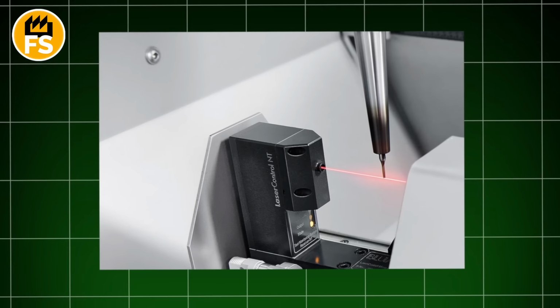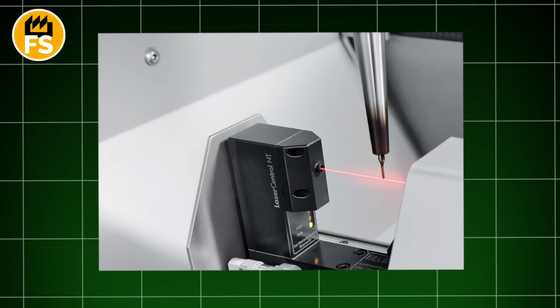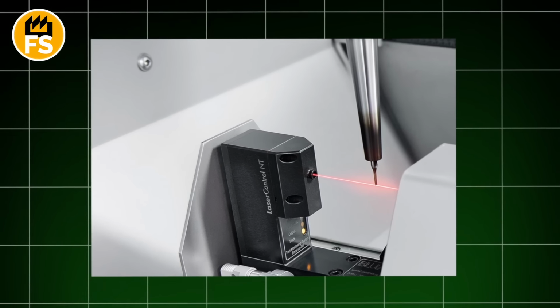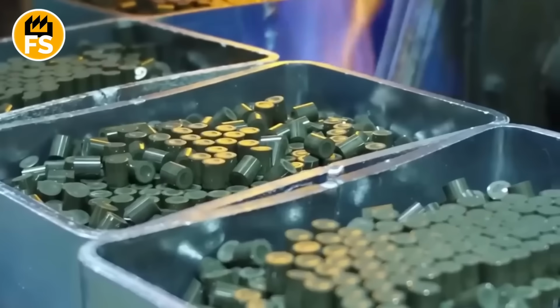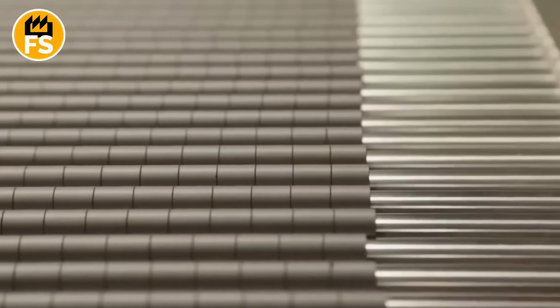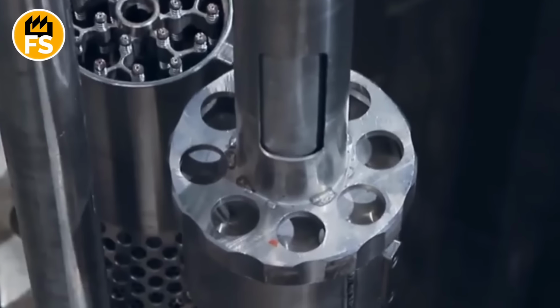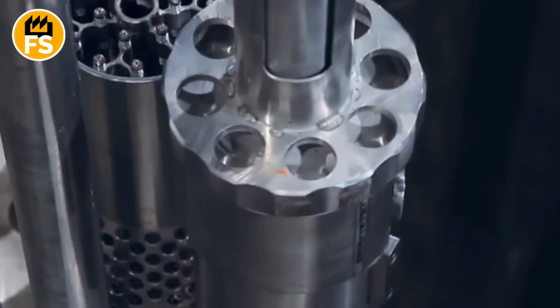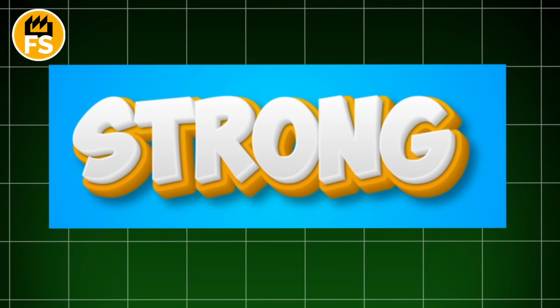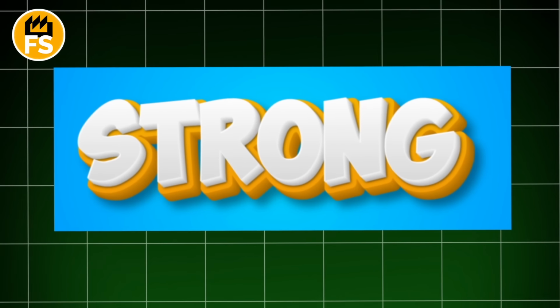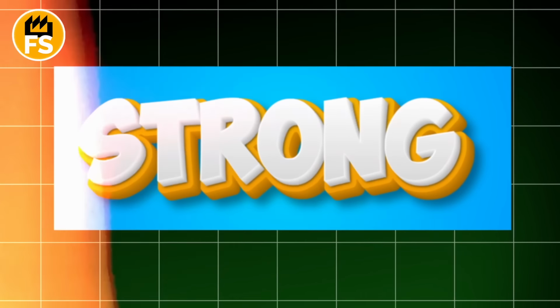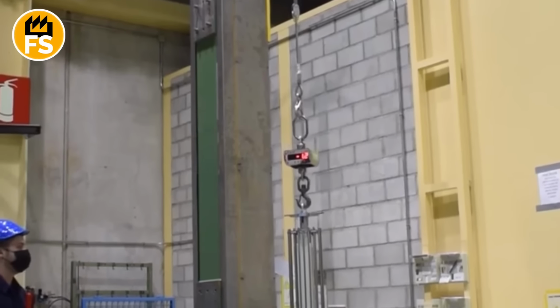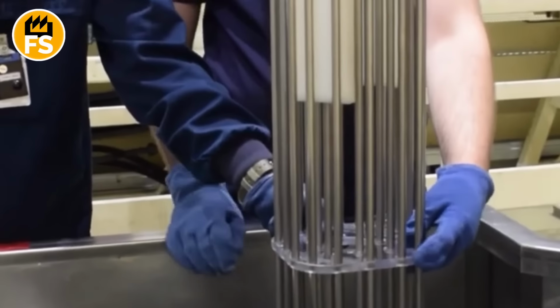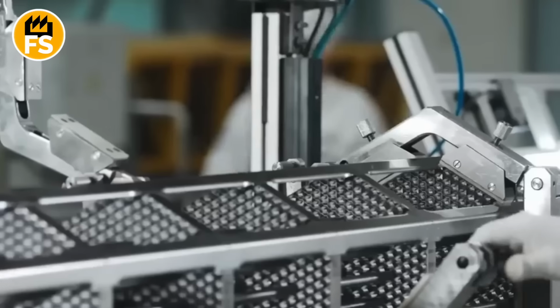Each pellet after this undergoes laser control, which checks its dimensions with micron accuracy. The next step is assembly. These small black ceramic candies are carefully, one by one, loaded into long, thin tubes. These tubes, about 13 feet long, are not made of steel, but of a special zirconium alloy called zircaloy. This material is unique in that it is very strong, resistant to corrosion, and most importantly, almost transparent to neutrons, allowing the chain reaction to proceed without hindrance.